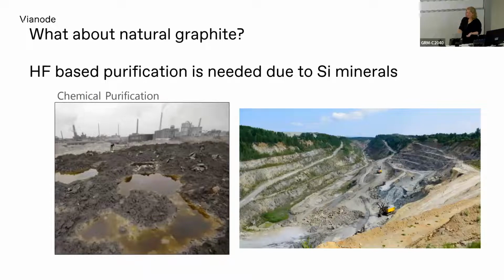If you are very interested in the battery material industry, you might also ask, well, what about natural graphite? Because of course, things that are natural are always very nice, right? It's just sitting there in the ground. Instead of having synthetic graphite that has to go to such a high temperature, you can use natural graphite. But what we see from natural graphite is that you cannot use it just from the ground. It's not like you pull the natural graphite out of the ground and it is ready to use as an anode material. It has to be chemically purified.